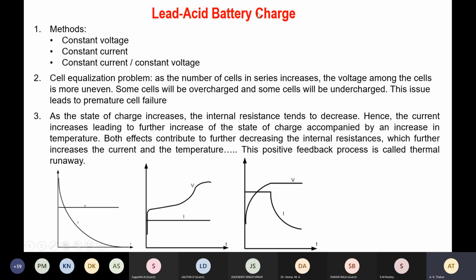So the ideally recommended lead acid battery charging methods are constant voltage or constant current, or sometimes constant current followed by constant voltage. The third option, constant current followed by constant voltage, is considered the ideal method of charging, because when we charge through constant current method, then as a function of time, it allows optimal voltage to be achieved. But the net designed energy may not be achieved, and for that constant voltage charging is a mandatory requirement, and the same charging method is adopted for lithium ion cell as well.